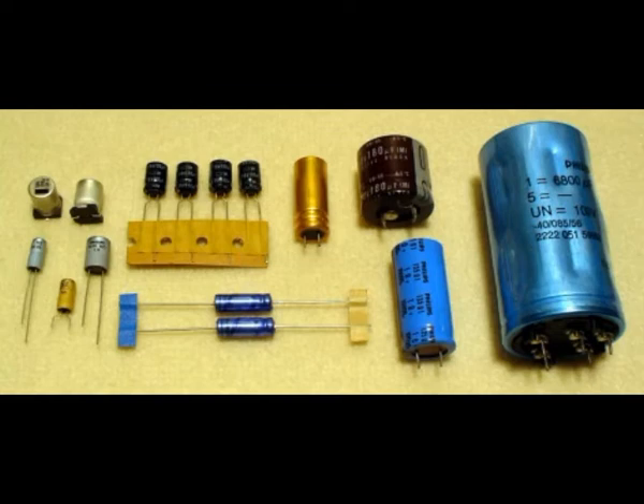The leakage current depends on the applied voltage and the ambient temperature. The value during continuous operation at 85 degrees Celsius is approximately 4 times higher than at 20 degrees Celsius. Otherwise the value is approximately 1/2 when reducing the applied voltage to 70% of the rated voltage. If non-solid aluminum electrolytic capacitors' leakage current after an operation time of, for example, 1 hour remains at a higher level than specified, mostly they have been mechanically damaged internally due to high mechanical stress during mounting.